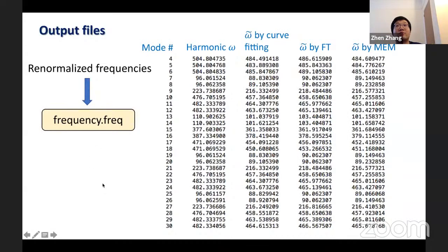Here I show some of the output files. The obtained renormalized frequencies will be written to the file frequency.freq. The first column are the indices of all the phonon modes. The second column are the harmonic frequencies. The third, fourth, and fifth columns are the renormalized frequencies obtained by the three methods: curve fitting, Fourier transform, and the maximum entropy method. As you can see here, for well-defined phonon quasi-particles and converged calculations, the three methods yield very close renormalized frequencies.